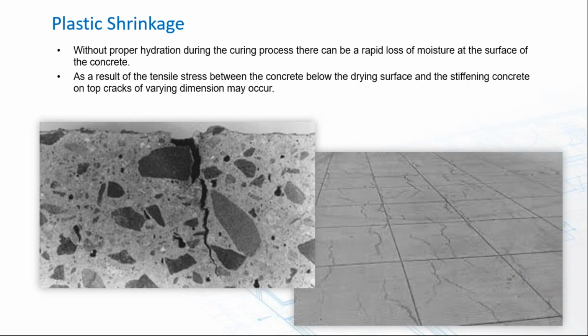Plastic shrinkage typically occurs during the hydration process, where there's a rapid loss of moisture on the surface, and as a result, tensile stresses between the softer concrete below and the harder drying surface above create some internal stress, and then we end up with cracks propagating through the concrete cross section, as you can see there, to varying depths. And once again, now it's a direct route for contaminants and chloride ions, particularly to start the journey towards the reinforcing.